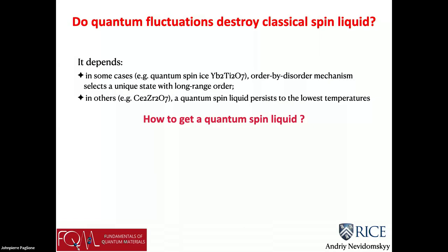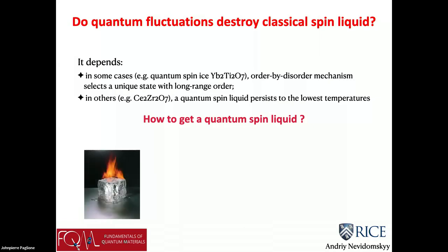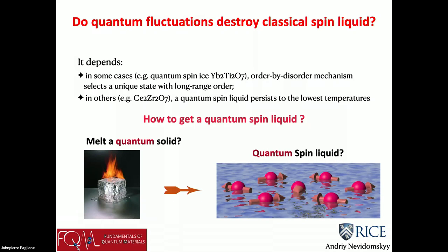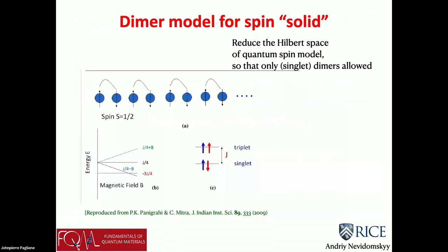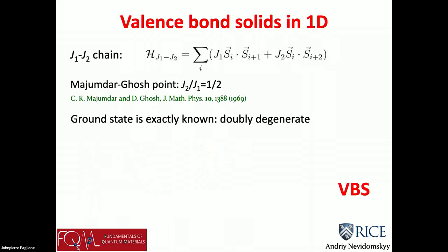So you could ask the same question I asked earlier: do quantum fluctuations destroy this or not? So if I start with a quantum solid, can I somehow melt it and get a quantum spin liquid? I just showed you a classical solid, and if you melt it, you end up with a classical spin liquid. How would you do it in a quantum way? One of the best ways of doing it is to think of dimers, because essentially, if you look at only two local spins that are Heisenberg coupled, they would like to form a singlet. So if you ignore the triplet configurations altogether and only allow for dimers, that allows for the rich concept of what's known as valence bond solids.